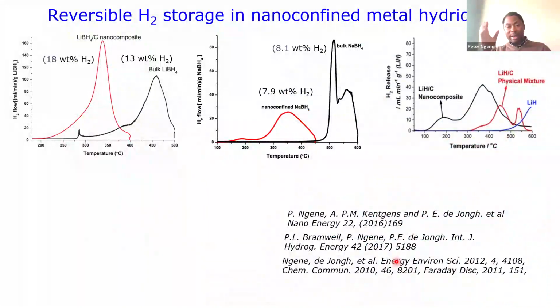Here I just want to give you an overview to show that this actually works, so you don't have to go into detail. We start with lithium borohydride. So this is the bulk lithium borohydride. So what do we do here? You have your sample, and then you heat it up, and you monitor the rate at which the hydrogen flows during the heating. And you can see that if you start with the bulk material, you need to go to almost above 400 degrees centigrade, almost 500 degrees centigrade, to get your hydrogen out.